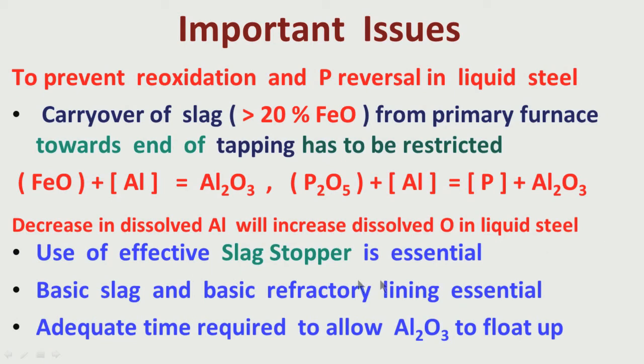So an effective slag stopper, I have told you, is very, very important. We must stop the slag from the primary steelmaking process, that means BOF or EF, from getting carried over to the ladle at the time of tapping.